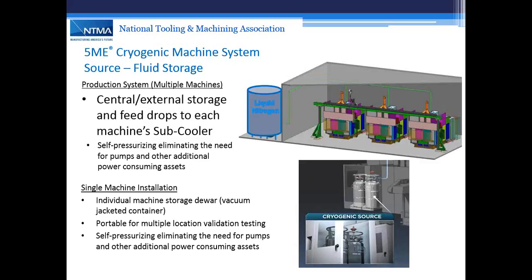As soon as liquid nitrogen heats up a little bit to ambient temperatures, it creates nitrogen gas. It boils at minus 321 degrees, of course. That expansion of the boiling of the gas creates the pressure to move the liquid nitrogen through the system. We're talking about very low pressures. Most transportation dewars are 22 psi. The systems that we build are anywhere between 30 and, at maximum on very large machine tools, up to about 70 psi. Again, very low pressures. Next slide.